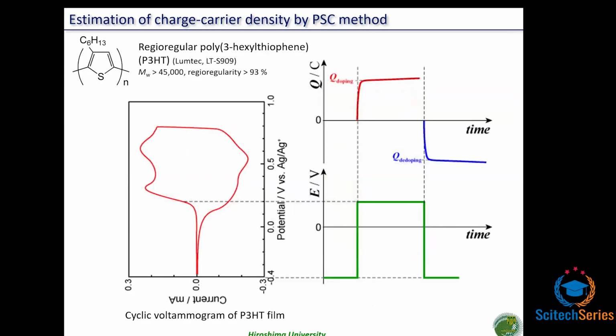Based on the information obtained from the cyclic voltammogram, the charge carrier density of P3HT can be estimated as follows. At first, the electrode potential was set at minus 0.4 volt. At this potential, P3HT is in the neutral state. Then the P3HT film was oxidized at a certain potential by stepping the potential from minus 0.4 volt, and the amount of electric charges generated during the oxidation process was recorded by the coulometer.